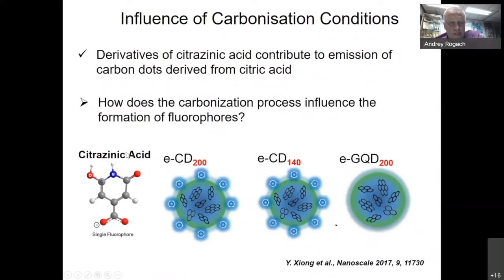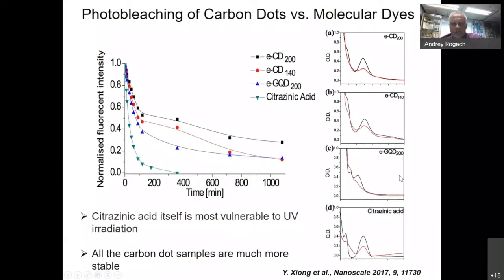So again, we took citrazinic acid, and then we ran reactions at 2 different temperatures, which are shown here by red numbers, 200, 140. And here we combine this citrazinic acid with graphene quantum dots. So we know that here there will be no fluorophores formed. And then we made our samples, and what we studied here was actually photobleaching of carbon dots as compared to molecular dyes. Because this is another advantage of carbon dots.